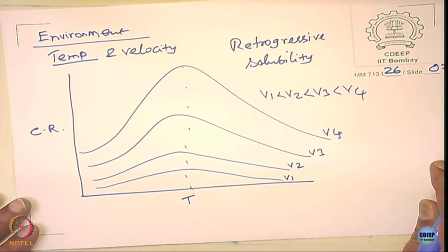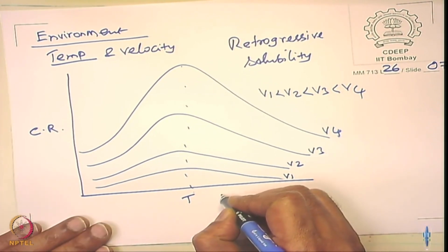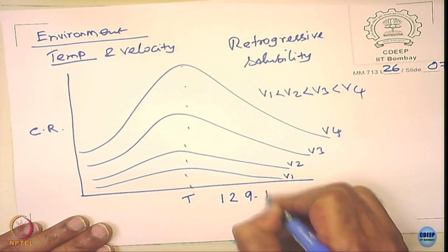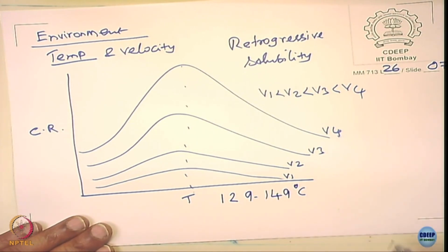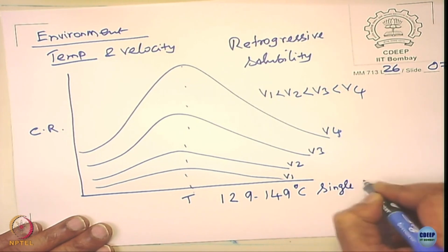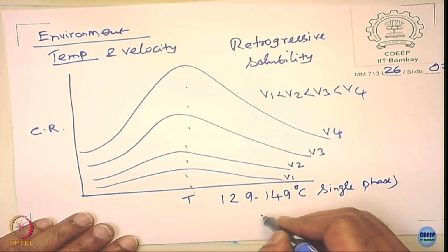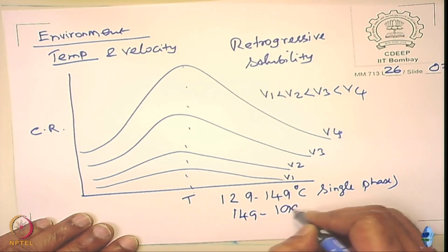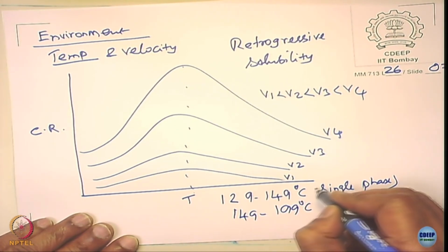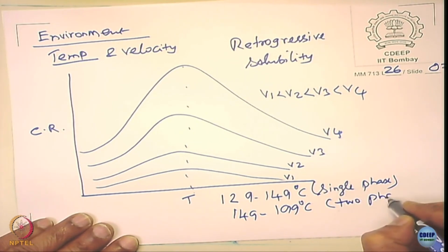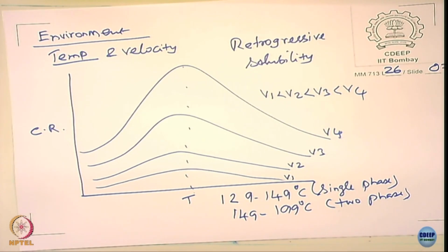And this temperature is in the range of 129 to 149 degrees Celsius for single phase flow, and it is in the range of 149 to 199 degrees Celsius for two phase flow. So what are the factors that can then control flow assisted corrosion? Velocity, the temperature, the pH.